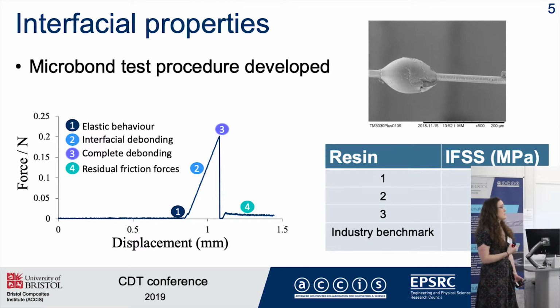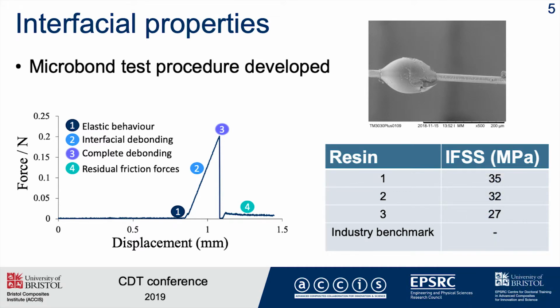I've developed the Microbond test procedure in-house for use here with a machine that we've bought, and looking at developing the test parameters for that. And I've had good results so far on the resin on glass fibre, and I've got the parameters, I think, now working. Sadly, I just ran out of time to get my industry benchmark value for this conference, but that is underway. But we're seeing good interfacial shear strength for the resin on glass.